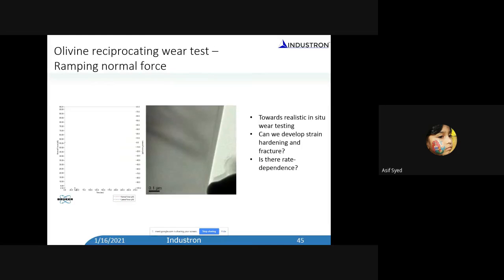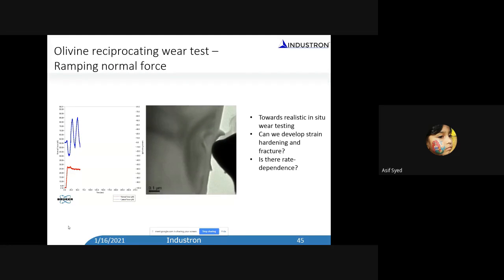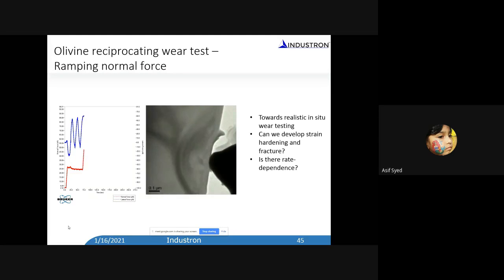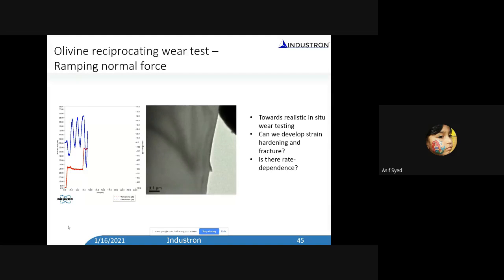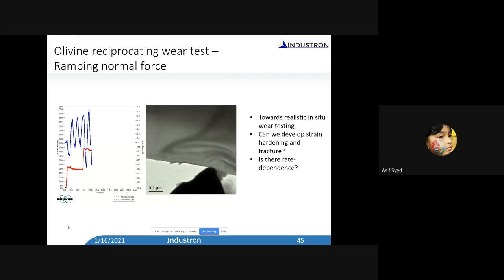Not only that, we can also do a tribology test inside the TEM, and we can do it in the SEM as well. Maybe I will play this video as well. You can see as you slide on the surface, you start to pop more dislocations. You can see the bands of dislocations that form. And by repeating, you can see the material getting removed. At the same time, you can measure both the lateral as well as normal force, and you can do that pretty nicely. So we started understanding the tribological characteristics. This is something that has been very elusive for tribologists: what happens when you slide beneath the sample? We now have a tool that lets us understand that.